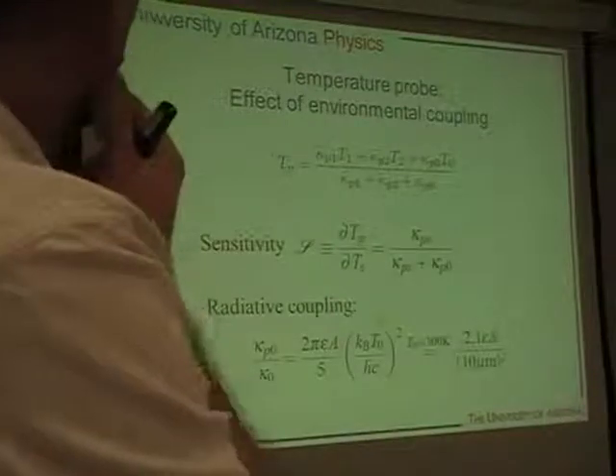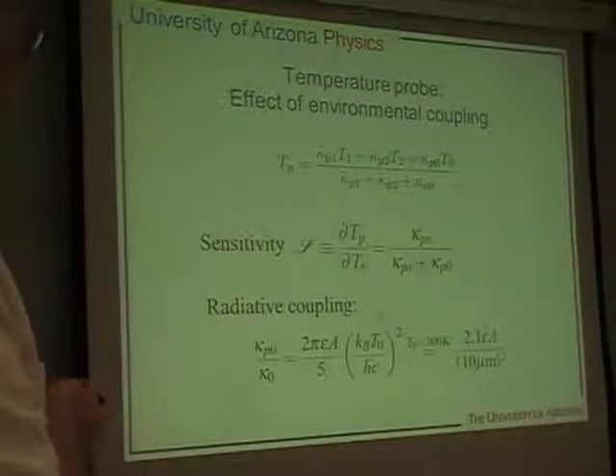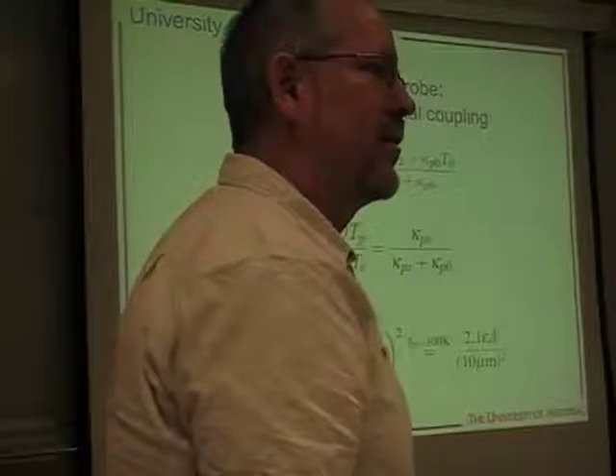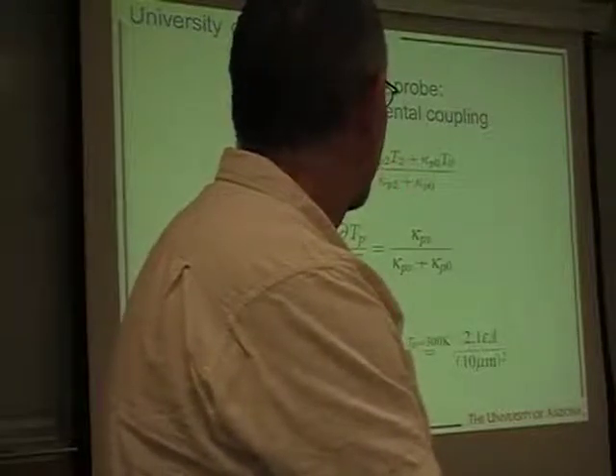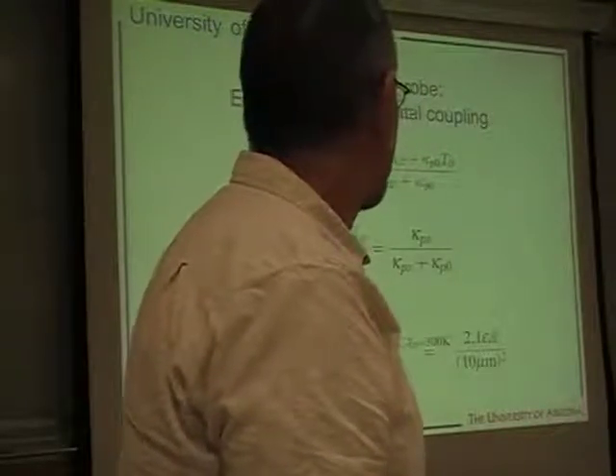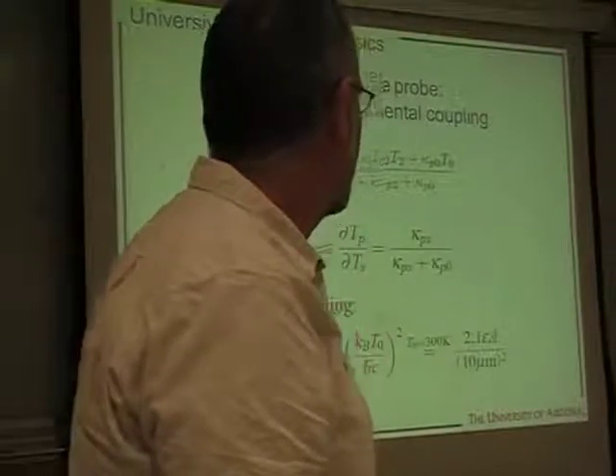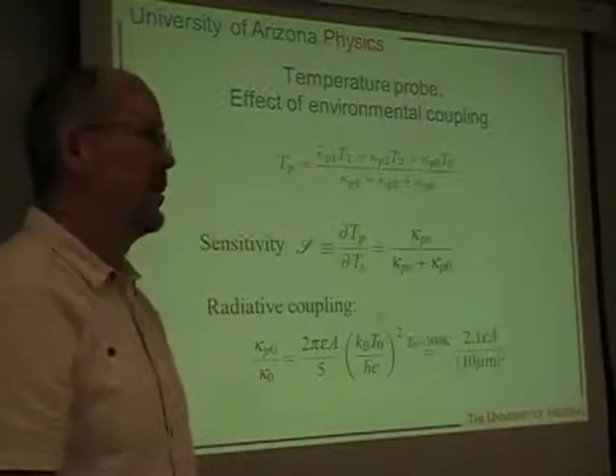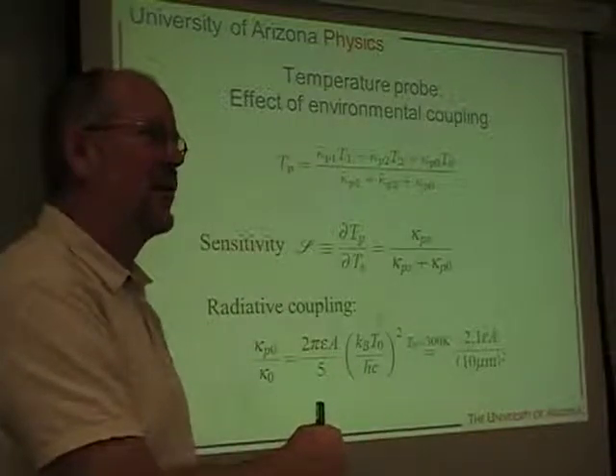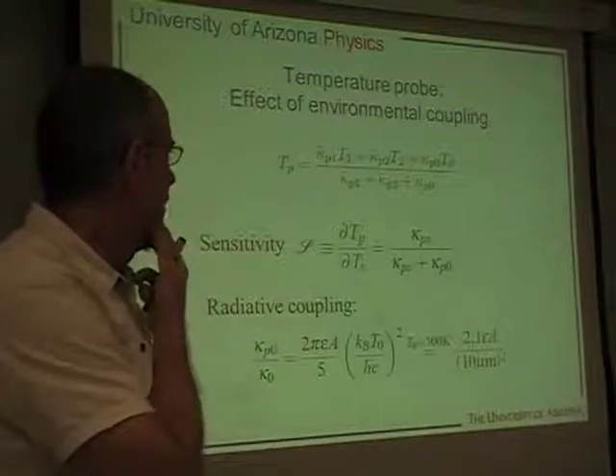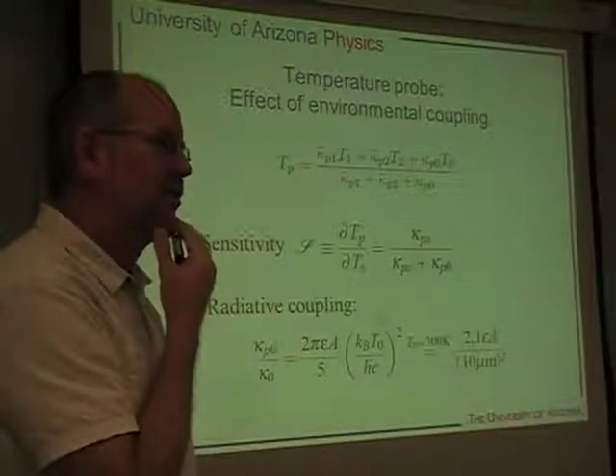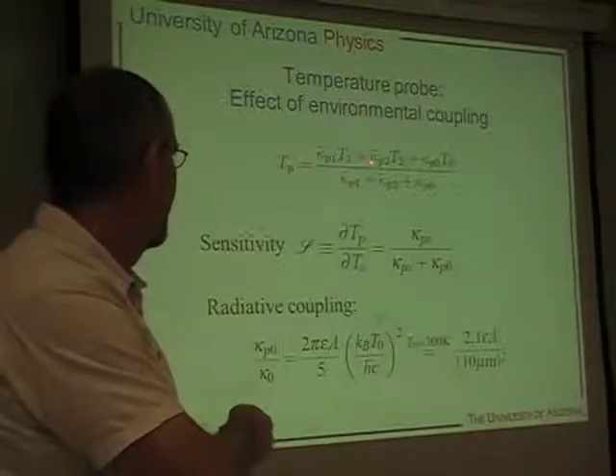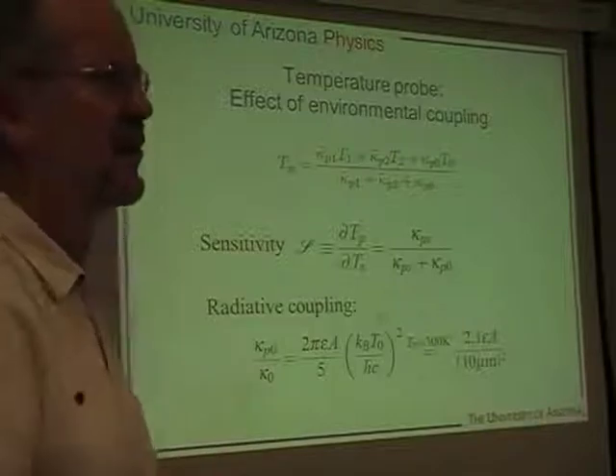I don't think that there would be. Because if you think about the electronic properties of the system, they're not very different at room temperature than at millikelvin temperature. So I think these guys wouldn't change much. What you would probably change quite a lot is the coupling to the environment. I think technically it may be challenging to heat the system and still keep it at a very cold mean temperature. But I don't think there would be really much difference. Certainly the calculation of these guys would be very, very similar at very low temperatures. So room temperature, it doesn't make that much difference.